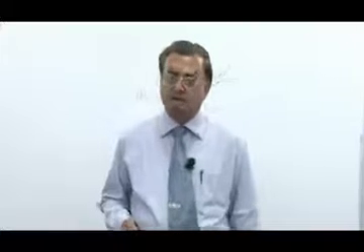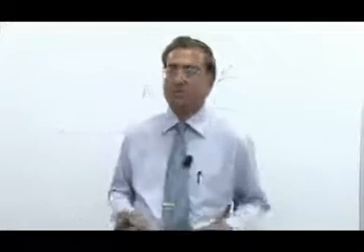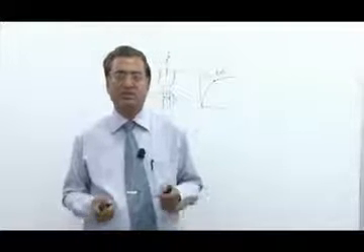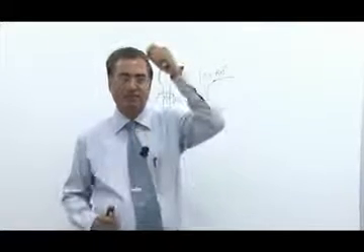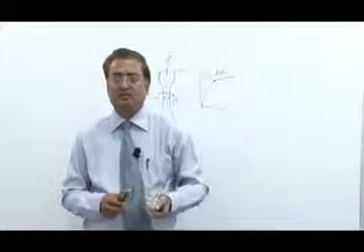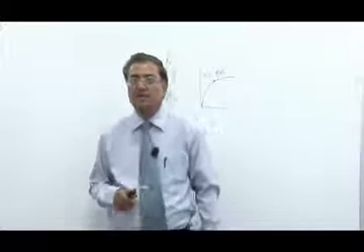Generally the tensile test is popular, but the notch tensile test is also carried out to evaluate notch sensitivity, that is, the tendency for reduced tensile ductility in the presence of a triaxial stress. In a simple tensile test there is only one axis. When it is triaxial, it is more than one direction, and a steep stress gradient occurs, and therefore metallurgical or environmental changes also take place.